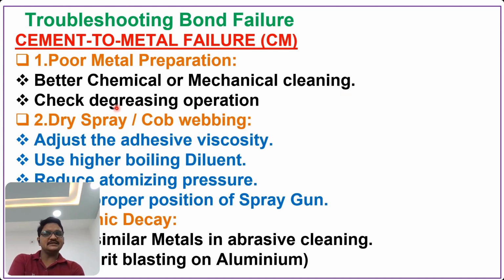We need to check the degreasing operation, meaning the degreasing tank may be dirty, maybe the chemicals are degraded. Second, we need to check the dry spray, meaning we need to open the spray guns. We need to check the spraying viscosity. We need to adjust adhesive viscosity. We need to use a higher boiling diluent. We need to reduce atomizing pressure. We need to adjust the proper position of the spray gun.